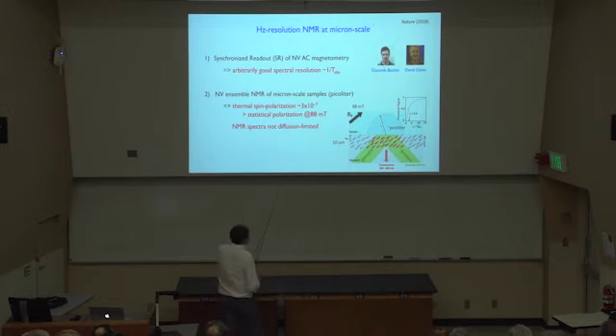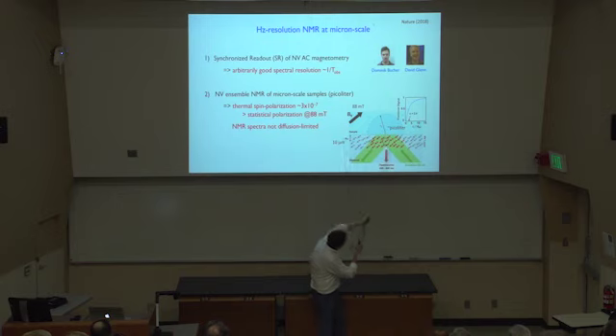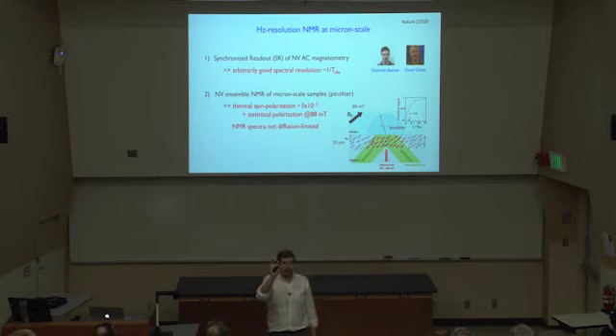So this is the kind of modality. Lots of NVs, maybe a 10 micron thick layer of dense NVs near the diamond surface, with the sample of interest on top, a picoliter-scale sample of a few microns. You come in with green light in a TIR mode so it doesn't go into the sample, and collect the red fluorescence, initially on a photodiode, essentially just a single point measurement. Later we'll do it in an imaging mode.